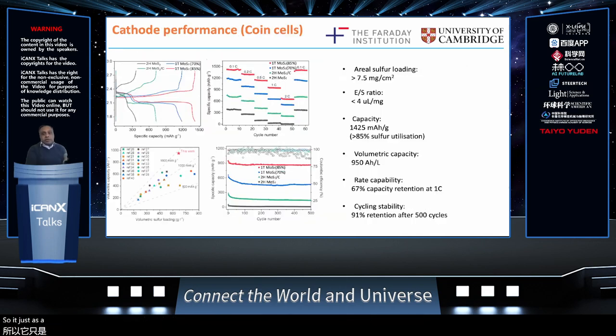So just as a summary of the coin cell data, I've discussed the galvanostatic charge discharge characteristics and the specific capacity. The areal sulfur loading, so you want to utilize a maximum amount of sulfur, that we can achieve is 7.5 milligrams per centimeter squared. The electrolyte to sulfur ratio that we use is much lower than 4 microliters per milligram. I'll show you in the next slide that with our pouch cells, we're able to go down to around 2.4 electrolyte to sulfur ratio, which is among the lowest that have been achieved. This gives us 85% of the theoretical capacity. We get good volumetric capacity and cycling stability.